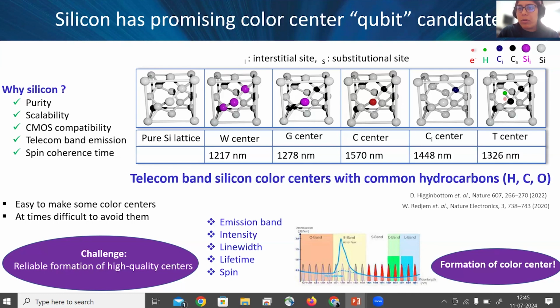So for example, if you look at the T center, in its structure, it has 2 carbon atoms, 1 hydrogen, and a free electron. Now, what you can directly do is manipulate the spin state of your free electron, and you can realize a spin photon qubit out of it. And similarly, in the CI center also, there is a free electron connected to the carbon, and you can manipulate the spin degree of freedom here, and you can have a spin photon qubit. So not all these color centers have a spin degree of freedom, but what they can provide at least is a single photon source, which is also one way of realizing qubits.